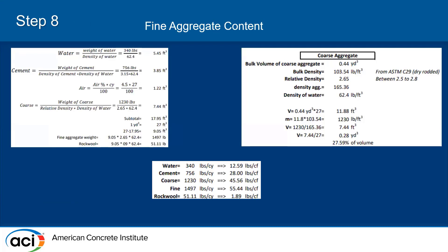Our main focus was the coarse aggregate. Using the sieve analysis provided by Quikrete, we found exactly what percentage of the mixture would be coarse aggregate. For the volume method, we mixed for a one cubic yard batch, converting all weights into volumes using the densities of our materials. The remainder of the cubic yard was used for the fine aggregate, then converted back to weight. Since we're replacing the fine aggregate with rockwool, we first calculated what would happen at 100% replacement, then adjusted the ratios to 75%, 50%, and 25% rockwool replacement.